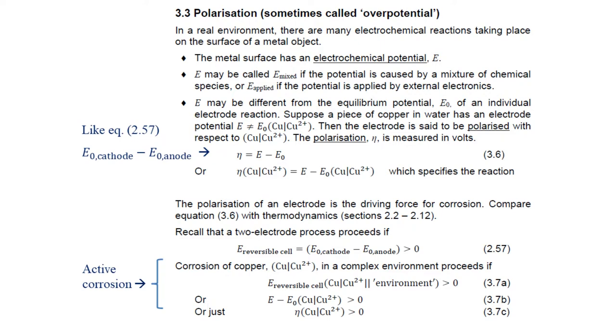Now, suppose, for example, a piece of copper in water has a surface potential E which is not equal to the equilibrium potential for the copper metal to copper 2+ ion electrode process. In that case, the electrode, the piece of metal, is said to be polarized with respect to the copper to copper 2+ electrode process. The polarization, which is called eta in algebra, is measured in volts. So, as in equation 3.6, eta is E minus E subscript 0.